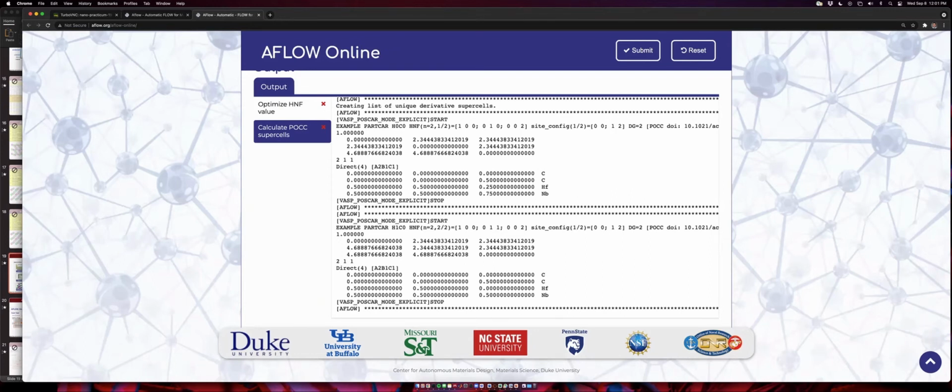No, really, if the energy of the disordered system is reproducible. Remember, energy is not a quantity that you can really measure. It's differences in energy. So the energy of the disordered system is not necessarily something that we verify. What we can verify are the properties of the system, something like band gap, something like the density of states, something like the Debye temperature. These are properties which we verified against experimental materials, what the literature tells us, and we do get very good reproducibility of the results. And not only that, but it has excellent predictive power.